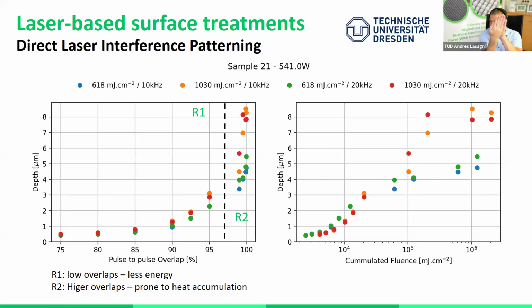That means we are pulsing, let's say, during the structuring process. And with enhancing the overlap, it means that a position of the material is irradiated many times. For example, 90% overlap means that we irradiate with 10 pulses, 95% is 20 pulses, 99% overlap means that we have 100 pulses coming to our surface at the same position.